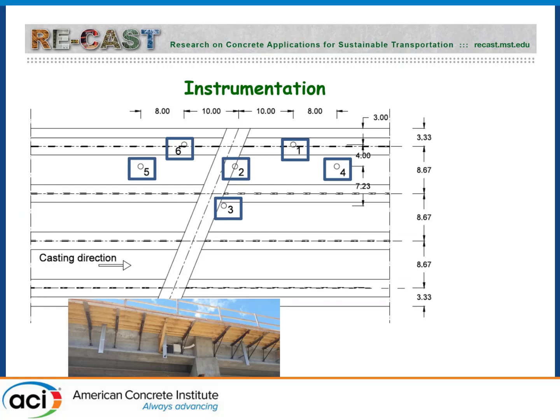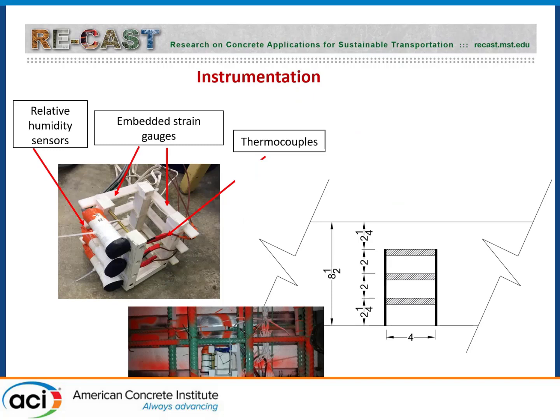And we expected a lot of tension, as I said, in the upper deck, not vertical, but in the longitudinal and transverse directions. So we put 6 baskets with instrumentation. This is a data acquisition system over here. It's connected to a solar panel with a cell phone to download the data in real time. And these are the baskets, and there are 3 sets of sensors. You have thermocouples, you have embedded strain gauges, and you have relative humidity sensors. Some of them we had to design in-house, like the relative humidity sensors, and we put them at 3 levels. As you can see, the bridge deck is 8.5 inches, so they sat at 3 different levels.